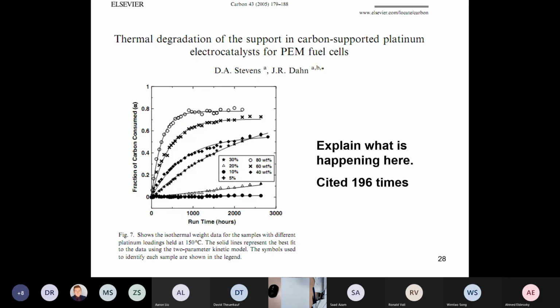Yeah, so when we got involved in our fuel cell work at the very beginning, probably around 2002, 2003, both Dave Stevens and I had a lot of experience with carbon. And we got a little bit concerned because imagine if you're putting the best catalyst in the world on the surface of the best support in the world, in the presence of the best oxidizer in the world. That's what's happening on the air side of a polymer electrolyte membrane fuel cell. We've got platinum sitting on carbon in the presence of oxygen. And we were wondering how stable this actually was.